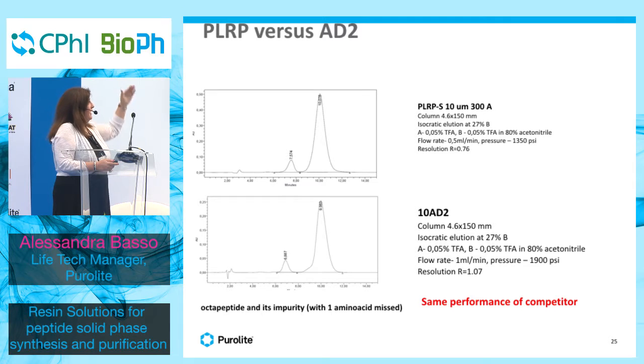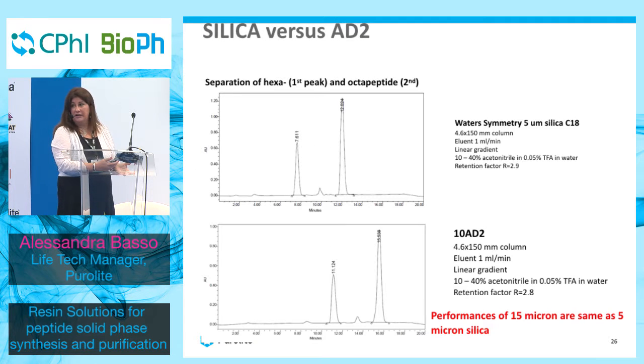Here we compare, again, the two with the same particle size. So 10 micron in both cases, and the separation is still good, better in our case. And this is a nice comparison with the silica material. On the top, there is 5 micron, so it's analytical HPLC, a silica material. And our material in 10 microns, so double the particle size, does not perform bad at all. So it's a good alternative to silica in some applications.